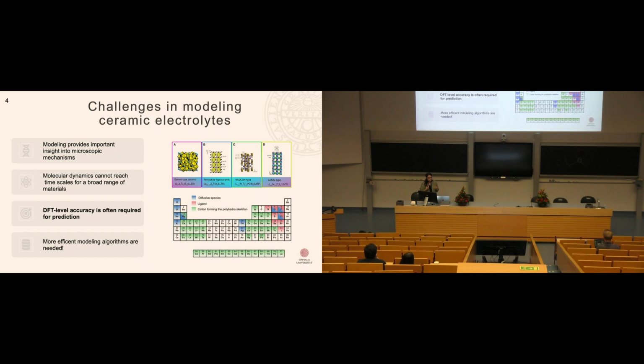This means that we generally need to go to a DFT level of theory to study the broader range of materials, and this additionally increases the computational cost of computing the diffusion at an ab initio molecular dynamics level of theory by many orders of magnitude, which then really limits the range of materials that we can probe the diffusion in to only the very, very fastest ion conductors.